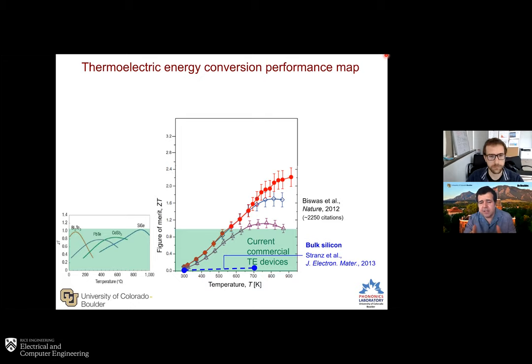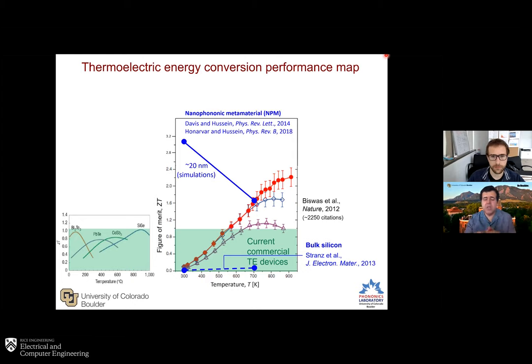However, as you can see, unfortunately, it actually performs very poorly as a thermoelectric material, roughly on the order of 0.01 or 0.02 ZT. So what I'll present today is a concept whereby we can take silicon, which in its original state is a very poor thermoelectric material, and turn it, by nanostructuring, into what we call a nanophononic metamaterial. And in doing so, we actually, in principle, project a quite remarkable increase in ZT.